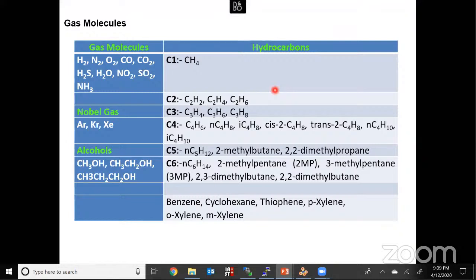And in this field, gas molecules as well as hydrocarbon materials are widely tested for the application of this material, to see what kind of MOF is suitable. For example, if you want to capture carbon dioxide, a MOF which has a nitrogen functional group in the linker will attract or interact with a CO2 molecule. If we have CO2 and CH4 in a gas mixture, that will trap particularly the carbon dioxide molecule. So if you want to separate gas molecules, you can use those kinds of material.